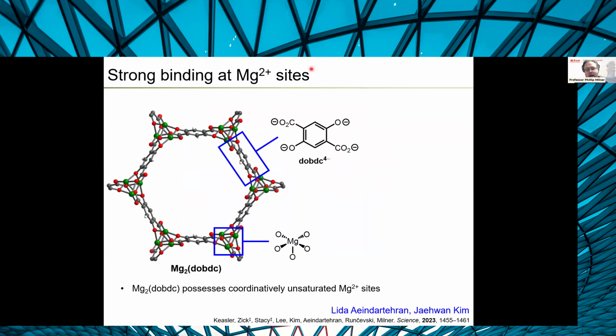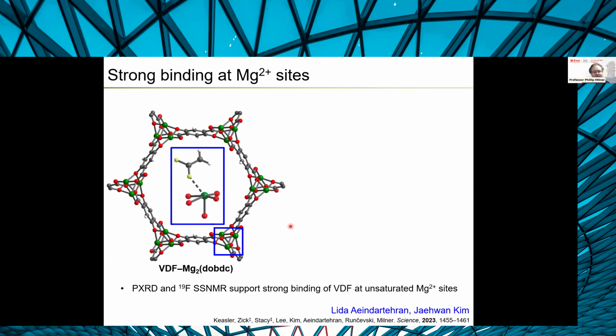Here's the linker of this MOF, but what really sets it apart, I think Mircea mentioned these open metal sites, is that this MOF has a very, very high density of these coordinatively unsaturated metal centers, in this case, magnesium sites that are missing an axial ligand. And if we dose them with the fluorinated gas, we were able to show by powder X-ray diffraction that they actually bind to this relatively strong magnesium fluorine interaction here.